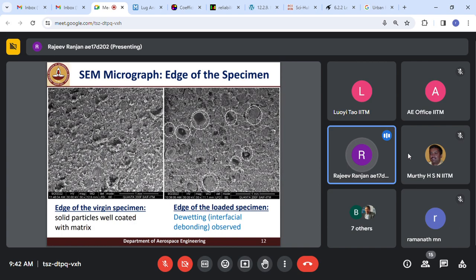In order to see how this compression loading is affecting the material, we have taken the SEM images of the surface of the specimen. This first image is before loading, and the second one is after the loading. We observed that in the virgin material, the solid particles were well coated within the matrix. However, when this compression loading acts on the material, dewetting happens, which was visible in the form of voids.